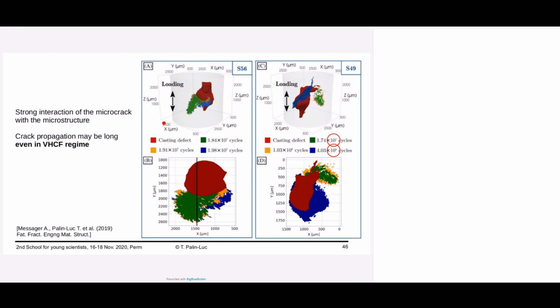What we have observed here is after reconstruction. So you can see here in gray the volume of the specimen in aluminum alloy. And you can see here in false color the internal defect in red, which is an artificial defect in order to localize where the damage will appear. And then we have observed the evolution of the crack initiation. So what you can see here in red, orange, and blue is the evolution of the crack after different numbers of cycles. And the two columns here show you two different specimens.